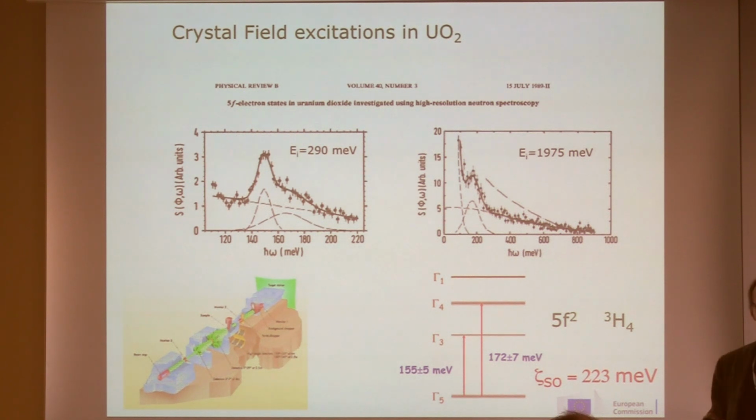We made some attempts at measuring this excitation at ILL in Grenoble, where there is a neutron reactor as a neutron source, using a hot spectrometer called IN1. And we failed because to measure magnetic excitations at high energy transfer, you need to satisfy two criteria: high energy transfer, but small momentum transfer, because otherwise you will kill the intensity via the square of the magnetic form factor.